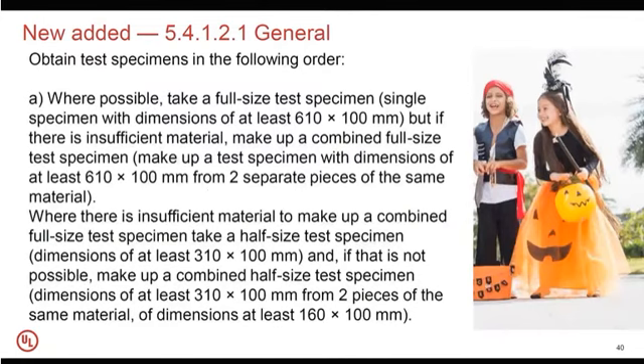Also has been newly added in chapter 5.4.1.2.1 how to obtain test specimen, to choose the correct order. So where possible, there is the need to take a full-size test specimens, but if there is insufficient material, there is the need to make up a combined full test specimens. So when there is insufficient materials also to make a combined up full test specimens, take a half-size test specimens, and if this is not possible, make a combined half test specimen to do the testing.